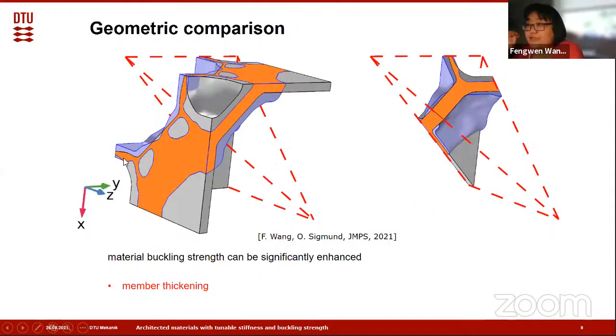This image shows the geometric comparison between the two designs, where the gray regions show the region owned by the macrostructure optimized for Young's modulus. The purple regions show the region owned by the macrostructure optimized for buckling strength. And the orange color shows the regions owned by both of them. We can see the material buckling strength is significantly enhanced by member thickening here.